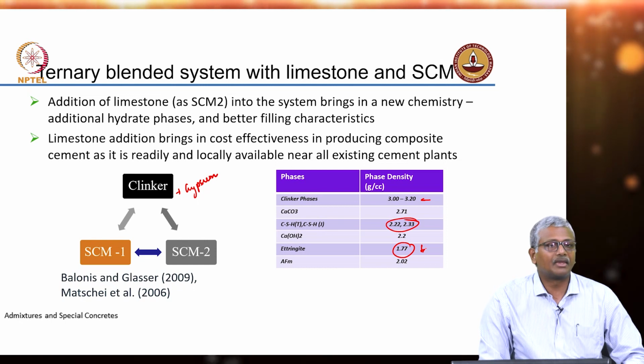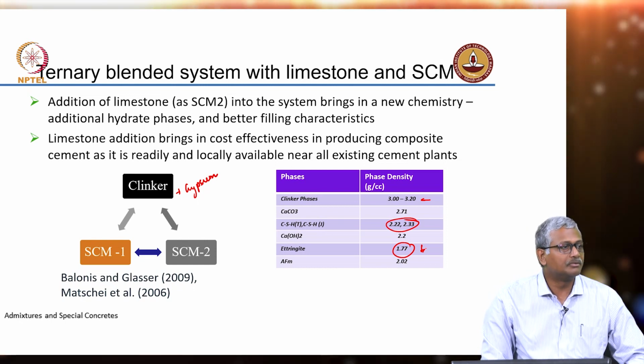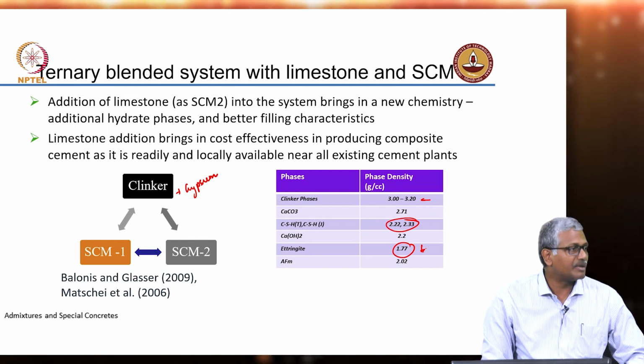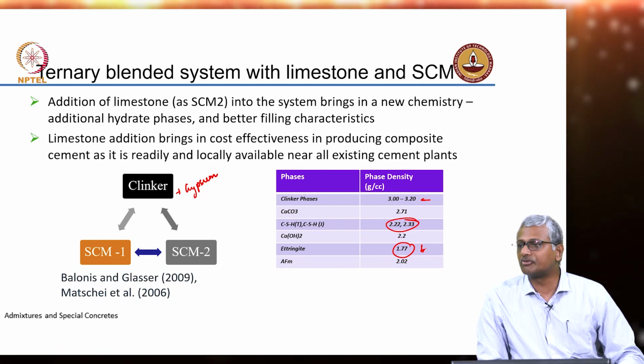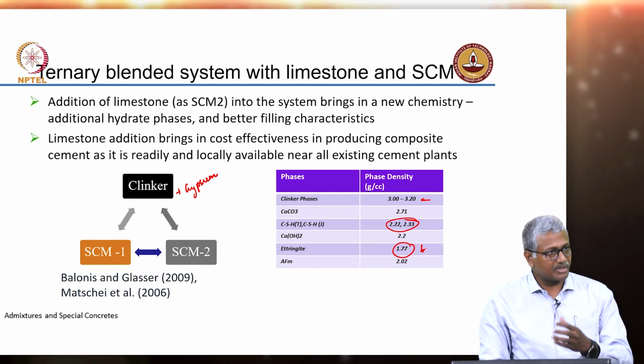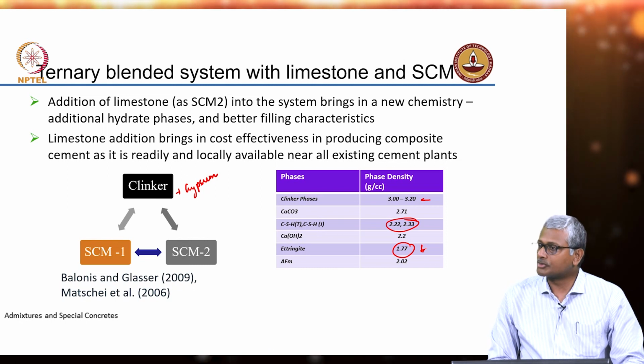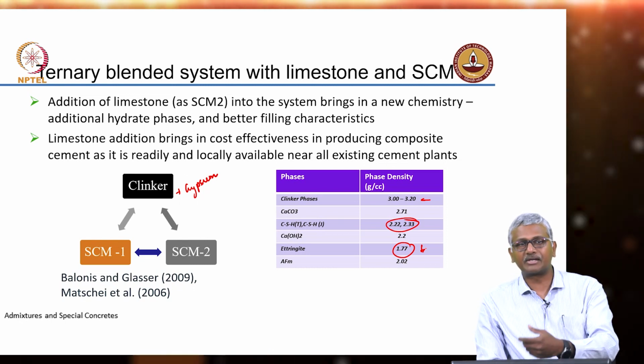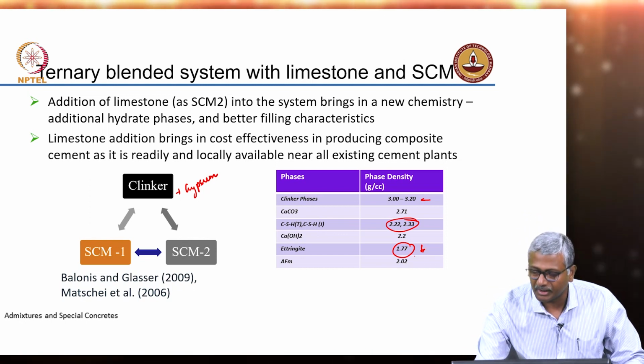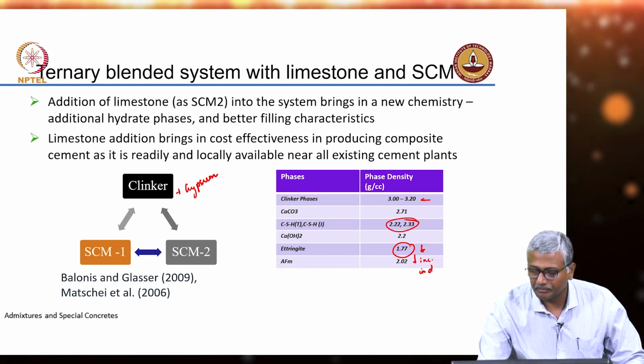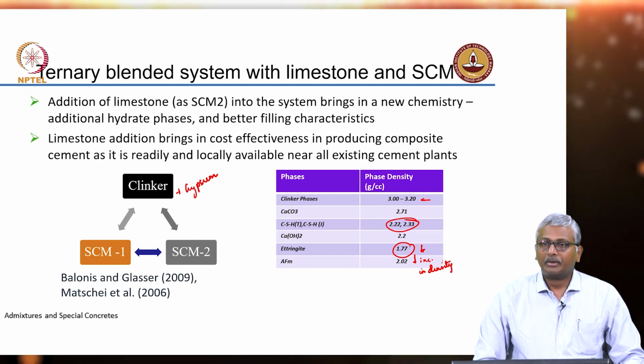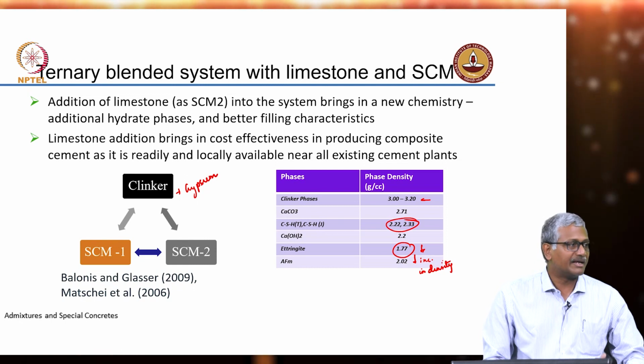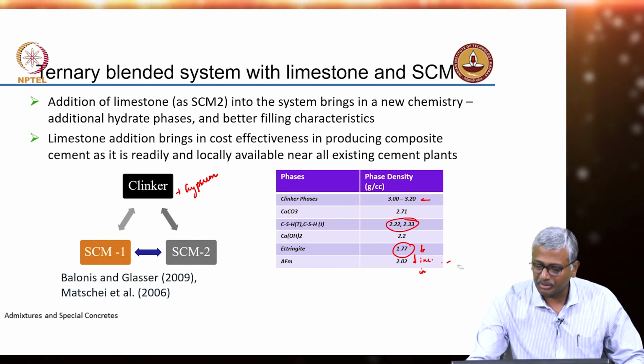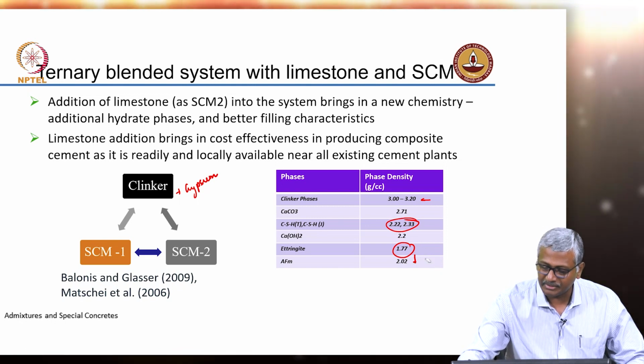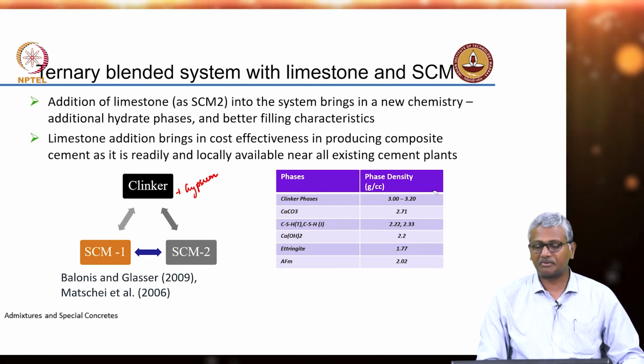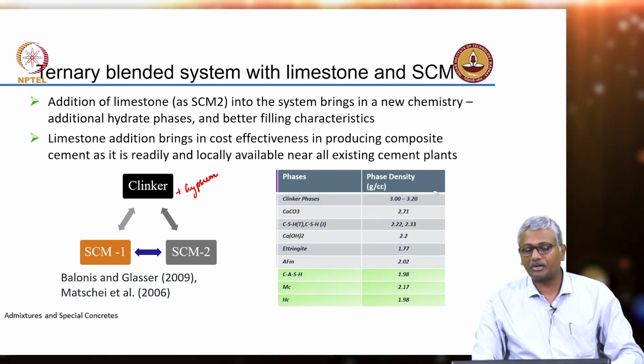What does this mean? If I form more ettringite, what does that mean? You fill up more space. Forming more ettringite means you're filling up more space. So if I choose a system where I can actually increase the ettringite formation, I can fill up more space. But what really happens in Portland cement, the ettringite gets converted to monosulfate and the density is going up. Right? So now my system is not as efficiently packed. But what will happen if I put limestone and another supplementary cementing material in conjunction with my cement phases is I'll end up with a different blend of hydration products.